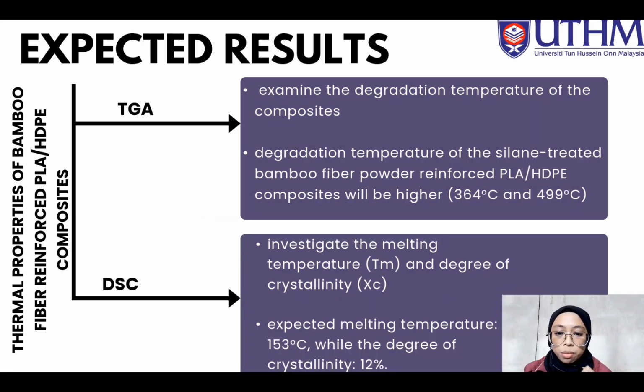Okay, next for the thermal properties, we use TGA and DSC. Firstly, TGA is used to examine the degradation temperature of the composites. The degradation temperature of the silane treated bamboo fiber powder reinforced HDPE composite will be higher, in the range of 364 degrees Celsius to 499 degrees Celsius. And DSC is used to investigate the melting temperature and the degree of crystallinity. We expect the melting temperature to be 153 degrees Celsius and the degree of crystallinity to be around 12%.